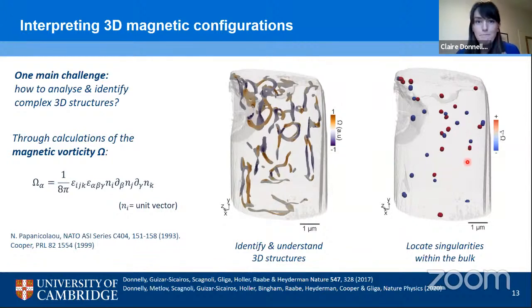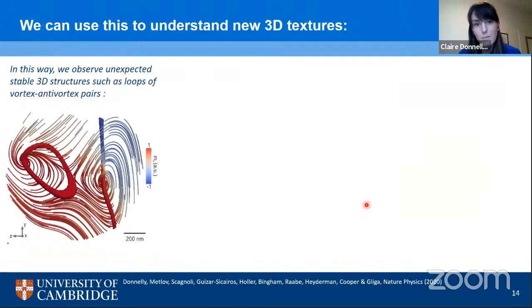But it's not just for the location and identification of topological magnetic structures that the vorticity vector is useful. It can also help us to interpret certain relatively intriguing magnetic configurations. One such magnetic configuration is this loop, which is made up of a vortex and an antivortex core, as you can see in this cross section here. This loop was particularly interesting because it's a sort of confined structure with a diameter of about 400 nanometers. So it's really a three-dimensional structure that appears to occur naturally within the bulk of our magnetic systems.